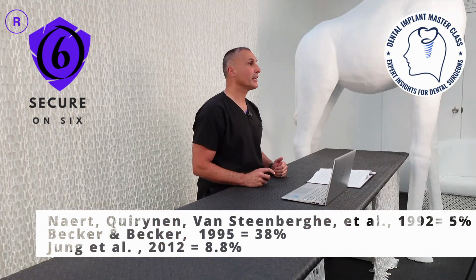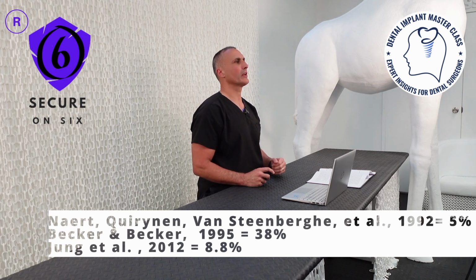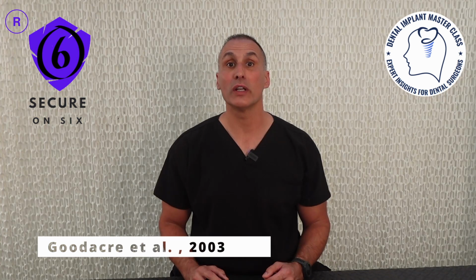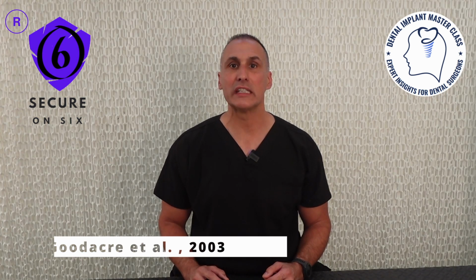Abutment screw loosening has been reported at various frequencies by different authors. Naert in 92 reported 5% incidence, Becker in 95 found a higher rate of 38%, and Jung in 2012 reported 8.8% incidence. Goodacre in 2003 noted an average loosening rate of 25% with early screw designs, which decreased to 8% with new screw designs.